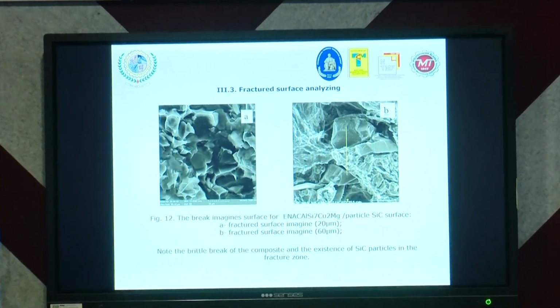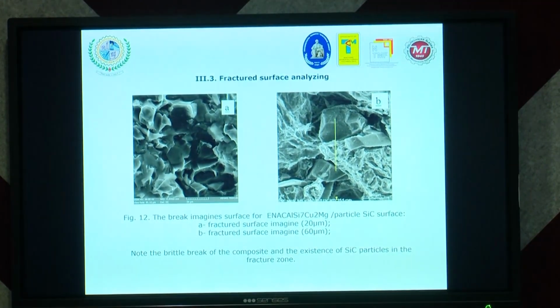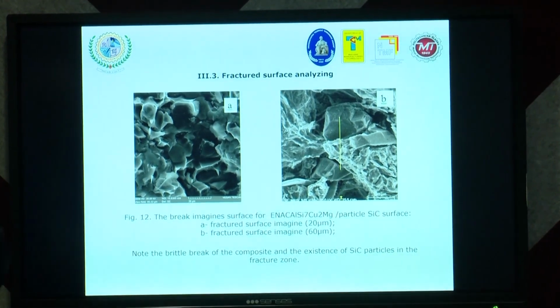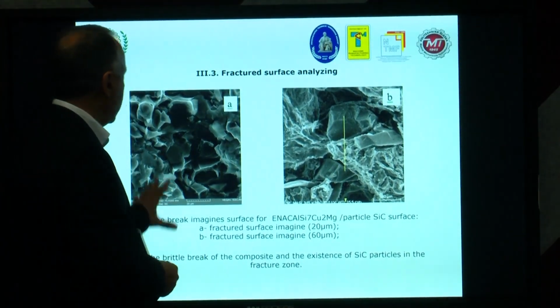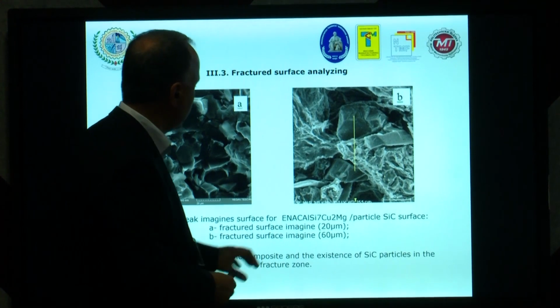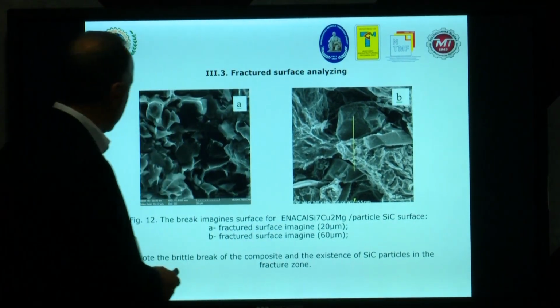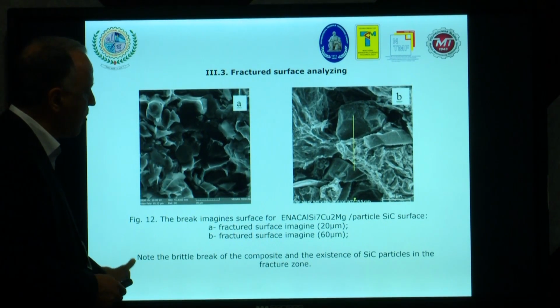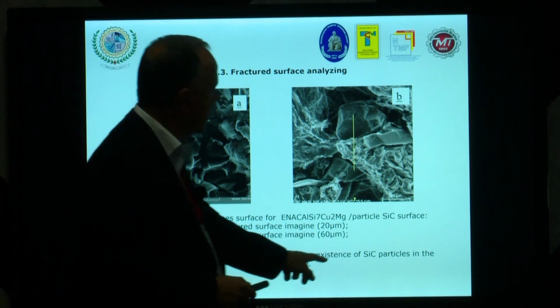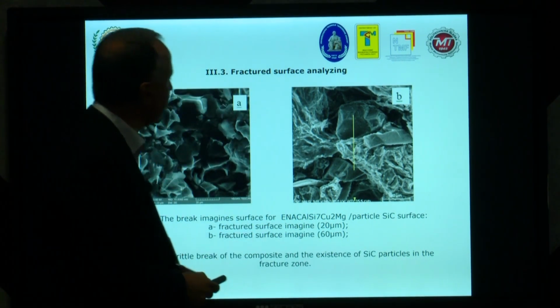The fracture images, I mean the breaking surface, with the particle reinforced. You can see in the case of 20 micrometers and in the case of 60 micrometers, brittle break of the composite and the existence of silicon carbide particles in the fracture zone.